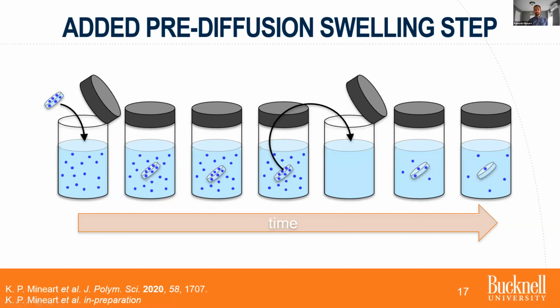And then once the gel is submerged in this oil with AOT, there's no concentration gradient. So there's no desire for the AOT to elute from the gel. And so this isolates the swelling step to this first half of the process. And then once the gel has reached an equilibrium swollen mass, we remove it from this pre-swelling solution and then repeat the experiment that I talked through before, wherein it's submerged in pure mineral oil and there's a concentration gradient which drives the release of AOT from these gels.